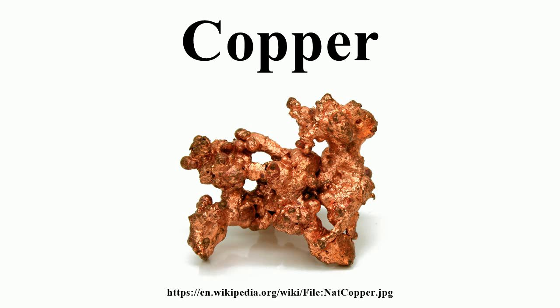The resulting copper matte, consisting of Cu2S, is then roasted to convert all sulfides into oxides. 2Cu2S + 3O2 → 2Cu2O + 2SO2. The cuprous oxide is converted to blister copper upon heating. 2Cu2O → 4Cu + O2. The Sudbury matte process converted only half the sulfide to oxide and then used this oxide to remove the rest of the sulfur as oxide.